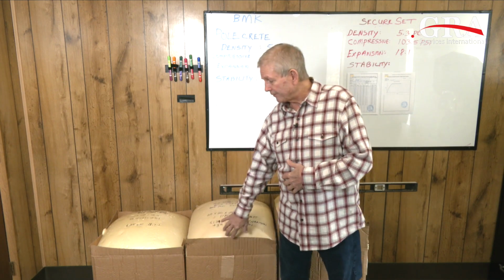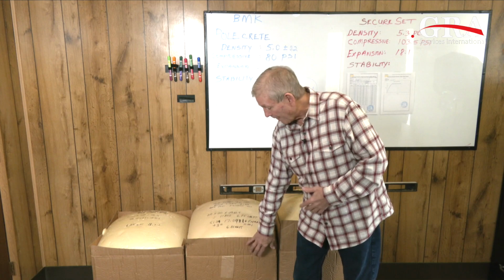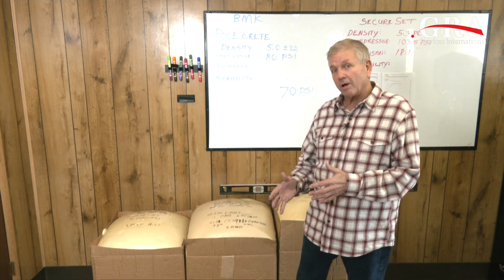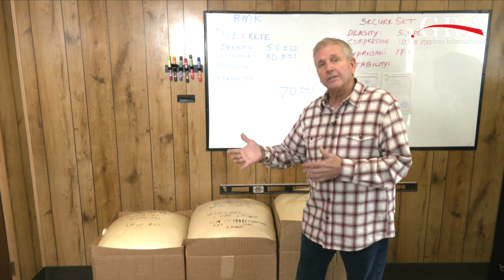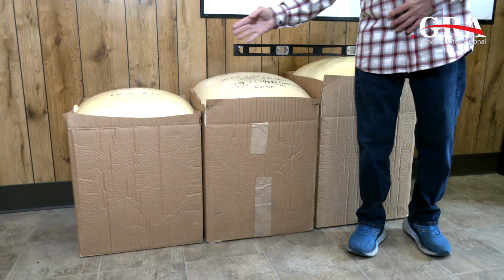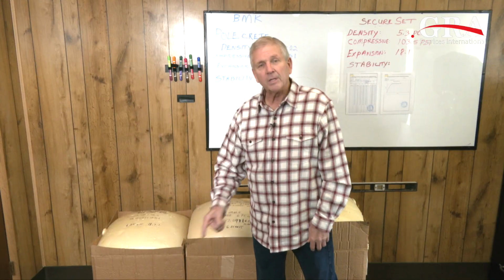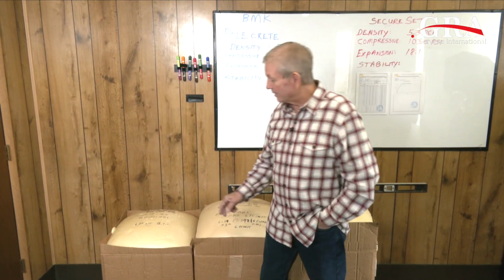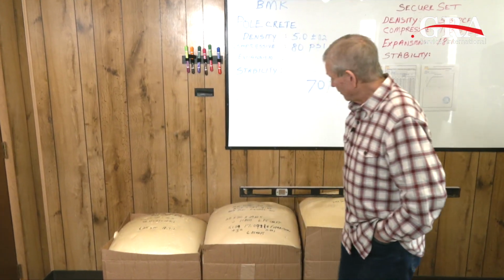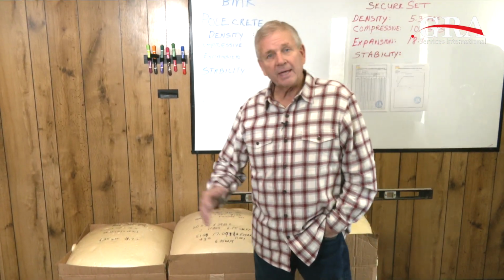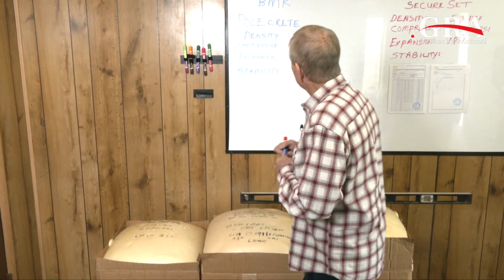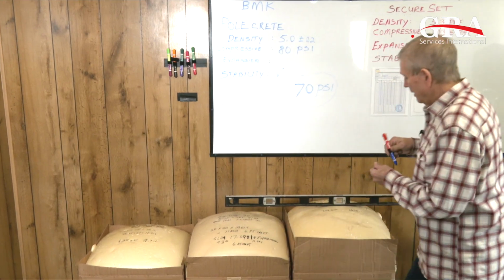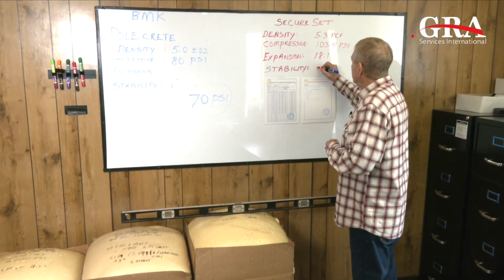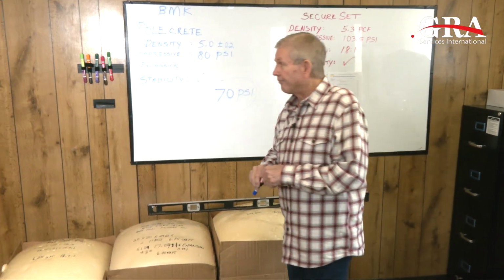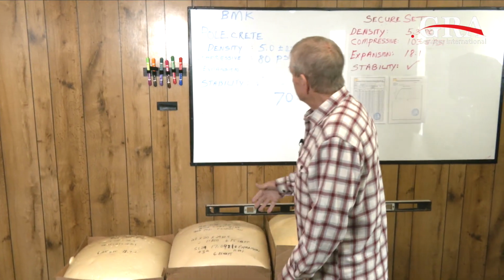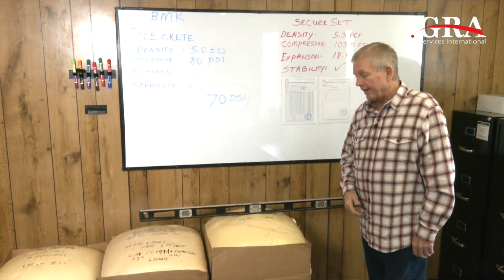Now, shrinkage shows up on these cardboard boxes in two forms. Number one, if any of these samples had shrunk, these boxes would pull into an hourglass shape. Now, as you can see, each one of the samples looks very stable. The other indication of shrinkage is a split or crack on the top of the foam. That did not happen. So from that perspective, we will have to say that stability for BMK and stability for Secure Set is confirmed.